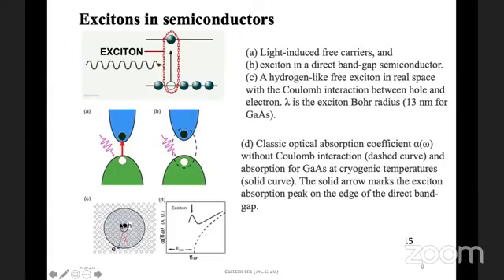Now, if we look at the bottom one, which is figure C, that electron is revolving around this hydrogen, which is a hole, and the radius of this orbit is known as the Bohr radius. When we have an exciton formed, we see a strong exciton peak in the absorption spectrum over here. When there is no Coulomb interaction, we see a normal absorption edge. But once there is a Coulomb interaction, which binds this electron-hole pair into an exciton, we see a peak over here.